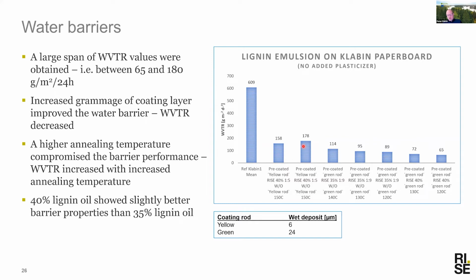The interesting part here is that this yellow rod has a little bit less deposition than the green rod here. So that is probably part of the explanation. But if we look at the green rod with the 35% oil, we see how it decreases. And when we had the 40% oil, we had a better response here. I got a question in the chat whether the lignin is unmodified.